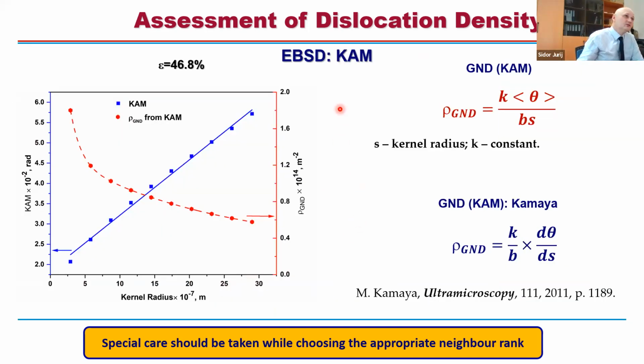So when you calculate the kernel average misorientation, one thing you will immediately see is that if you perform a measurement with a certain step size, then the GND you calculate will strongly depend on the step size and the neighbor you choose: first neighbor, second neighbor, and so on. So here we put the dependence of the GND on the so-called kernel radius, which is either step size or neighbor, right? In order to overcome this problem, Kamaya